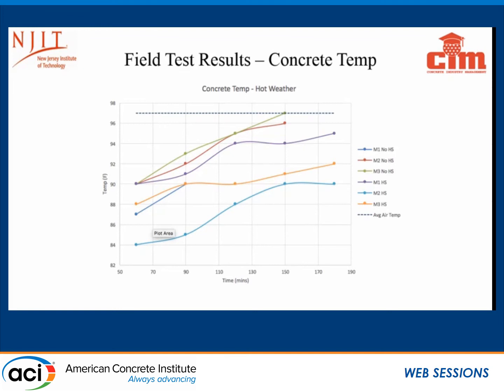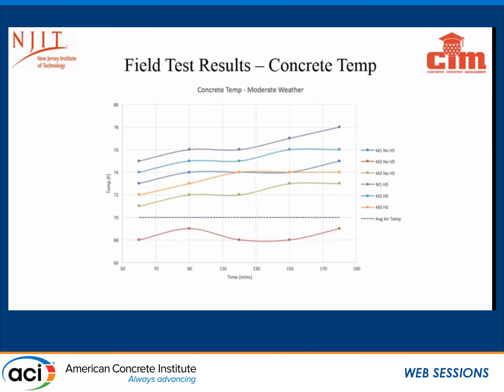Comparatively, you have the mixes here, with hydration stabilizers. You have about a 6 degree temperature rise in all of the mixes with and without hydration stabilizer, which is not significant. Okay. And then if we go to moderate weather, again, it's fairly consistent. The cooler temperature, of course, is going to play a role. The hydration stabilizer helped to maintain it, with an average air temperature of about 70 degrees leading into October.